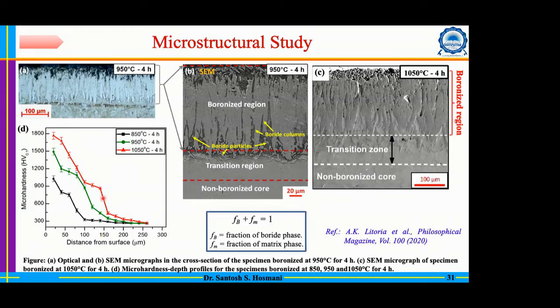That's why whenever we take an indentation, you're getting the information from boride as well as from the matrix. That's why you're getting very low hardness, or least hardness, at 850 degrees Celsius. However, at elevated temperatures, the matrix region is entirely occupied or consumed by the boride. That means that region will have only boride. So during microhardness measurement, you're getting information only from the boride. That's why your hardness is very high there.